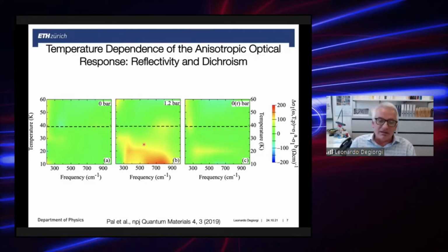This is somehow at variance with what we have observed in the past in the underdoped regime, where the stress-induced anisotropy was observed, even with a hysteretic-like behavior, by the way, all the way up to an electron volt away from the Fermi level, so rather deep into the electronic structure, which was indicating some important ferro-orbital mechanism, or was somehow signaling some ferro-orbital-like scenario driving the nematic phase transition. This ferro-orbital type of coupling seems to be somehow negligible or not so prominent as far as the optimally doped regime is concerned.